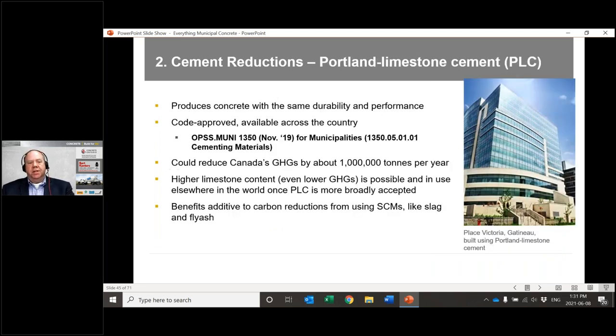The other one that's been addressed in the OPSS standards is Portland limestone cement. So that's just blending in with conventional GU cement. There's about 5% limestone. So it's the rock material that hasn't gone through the cement kiln that we run with the clinker through a ball mill to create the fine cement powder. So instead of just using 5% in Portland limestone, we increase that to up to 15%. And because that limestone didn't go through the cement kiln, it has a much lower carbon footprint, and we can get about 8 to 10% reductions in CO2 from that.